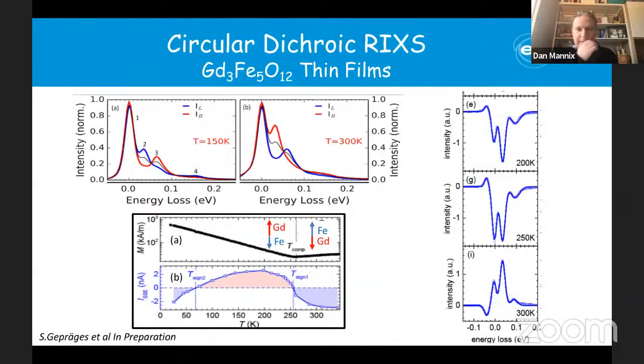But what I really wanted to share was what we could do also with RIXS. We've been doing RIXS experiments at I-21 at Diamond and at ID32 at the ESRF. This is some recent data where we use circularly polarized light. In principle, circularly polarized light can give you information on chirality as well. So the idea was to see if we could see some differences in the magnon chirality using these circular light probes, albeit with a broader energy resolution.